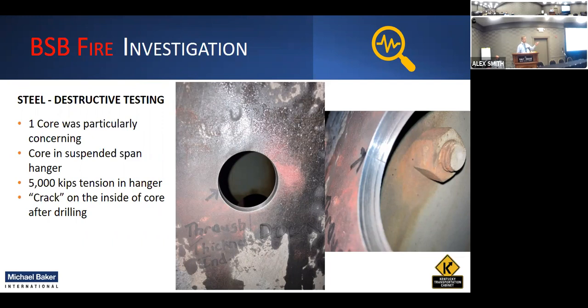While they took the core out of the cover plate for this big box section that's the hanger, a notch, or a crack indication, was noted after the core came out. Talking to people, we looked at it, we tried to take some pictures, you can see a little bit of it there. And so there was an immediate concern. Why did this little notch occur? Why did this crack occur in the steel? Was this overly brittle? Is this thing going to propagate? Do we have additional issues from this fire that we don't understand?